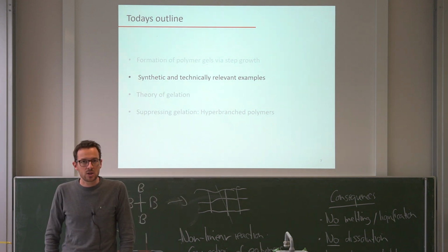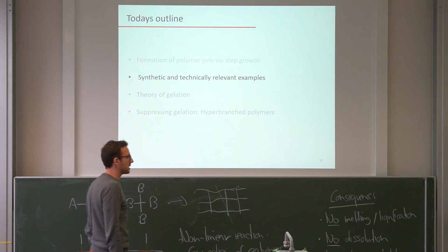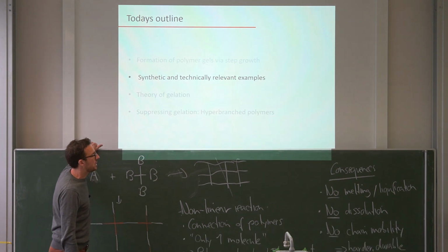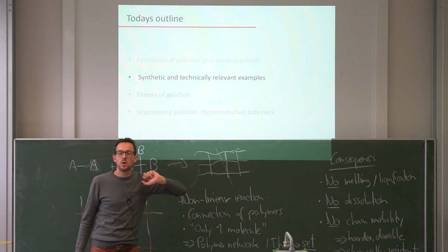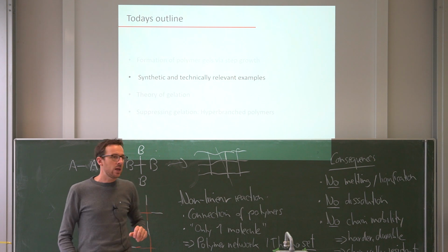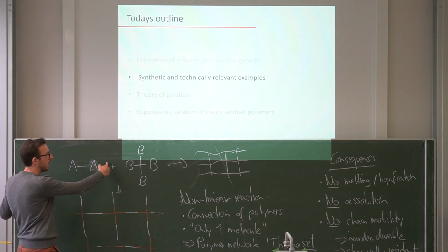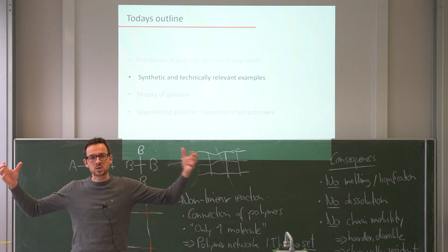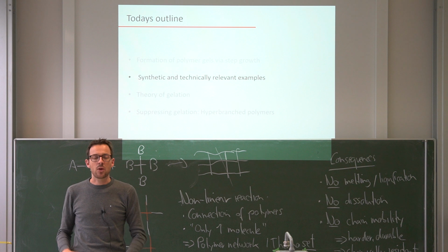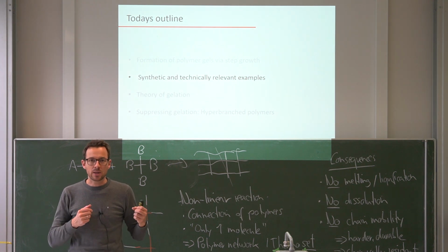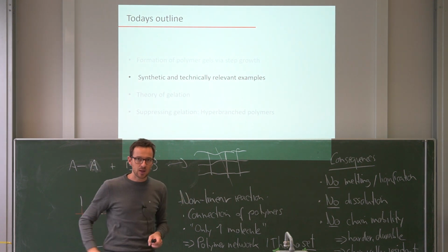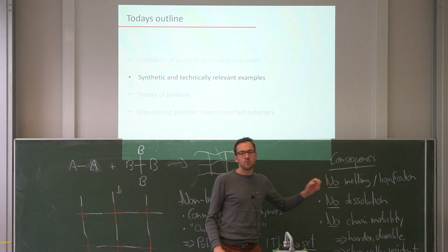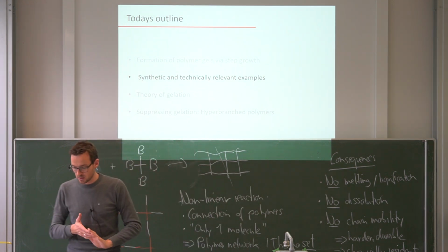Maybe one additional point: what we discuss here in this context of thermosets and hard and durable materials is when we really have very close networking points. The situation is somewhat different if we have really long polymer chains A or very little amount of B. Then we have a very loosely linked polymer network, and this we typically call either a polymer gel or an elastomer. But this is something I would like to discuss a little bit later in one of the following lectures, and here we'll mostly focus on examples where we have these tightly connected materials.